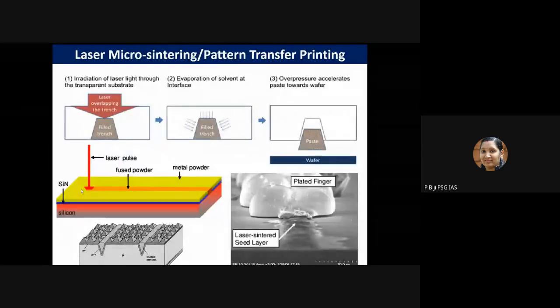The main challenge for solar cell metallization is the investigation of laser processing parameters. You need to apply enough energy for powder fusing and bonding to the cell surface without damaging the thin, preferably doped, emitter surface. It should not be destroyed, but at the same time you can get high aspect ratio as well as narrow line width metallization using this technology. But again, the processing parameters are very complex. So that's why the technology was not very popular.